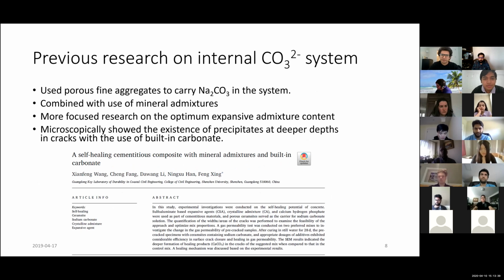This was one previous study that has been done in this regard. They introduced sodium carbonate ions internally inside porous aggregates, and then they added a lot of other things as well. But in their study, they microscopically showed that there is an existence of precipitate at deeper depths in cracks, not just at the surface.